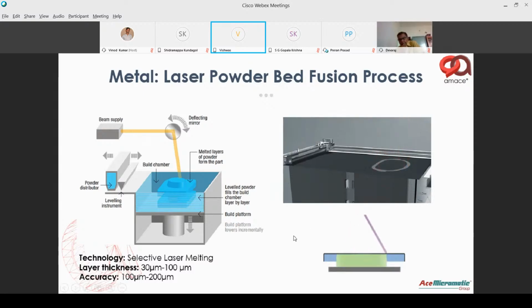The power source could be either a laser or an electron beam. What you see on top is a laser beam which is deflected by a mirror. It's a 2-axis mirror which deflects the laser beam very selectively and accurately at a specific spot, and then melts the powder and fuses it to the previous layer. This is very similar to a micro welding process, so any material that can be welded can be 3D printed. You have heard of laser welding. This is very similar, but happening at a micron level, a very fine level. That way you get your accurate part with very few defects.